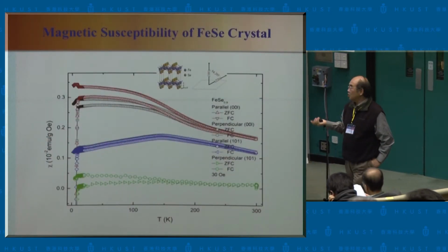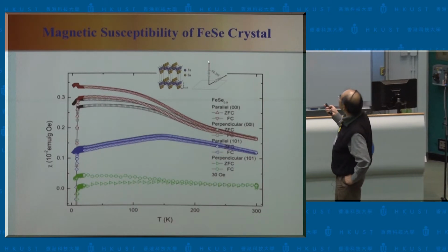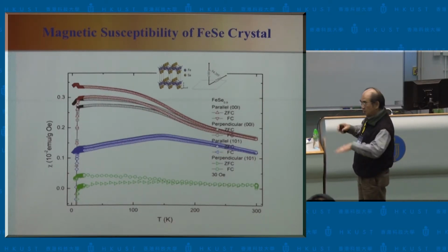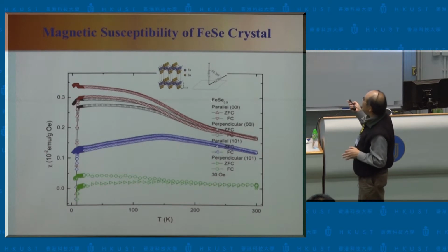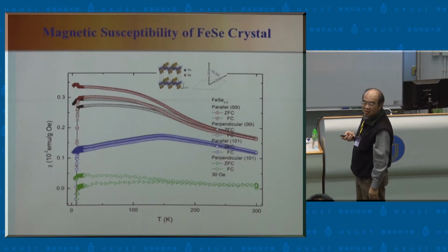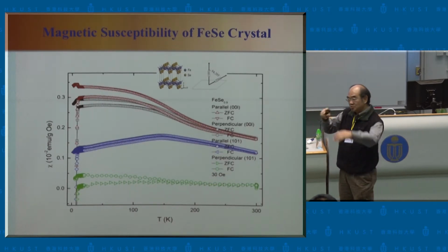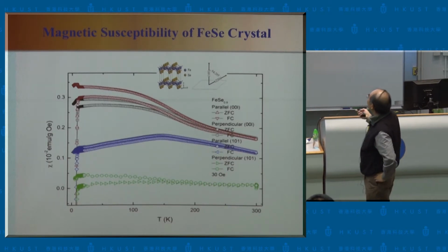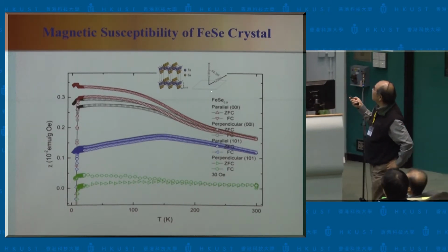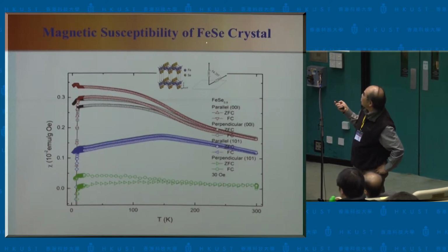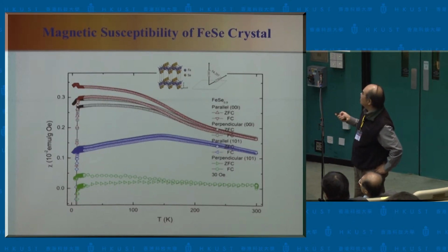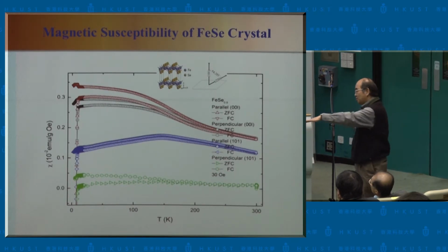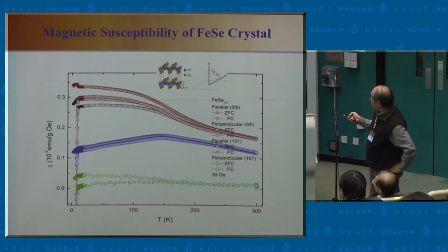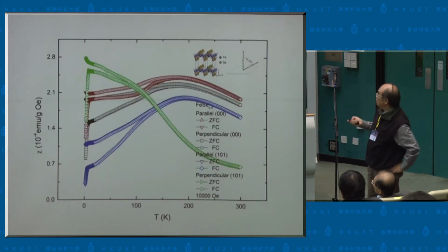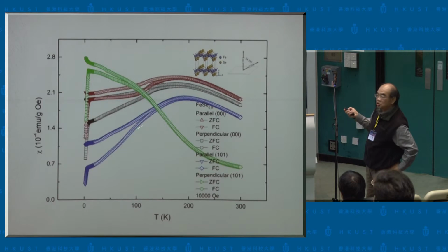More interesting, this is something we don't quite really understand, is that we were using this iron selenide single crystal. It's interesting that the crystal usually has a growth habit along the 101 surface instead of the normal 001, which means along this iron selenide plane. And if we look at the field along 101 and perpendicular to 101, and plot it, you see a strong anisotropy between these two directions.